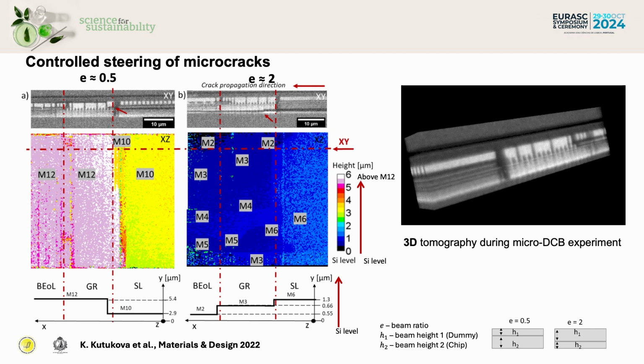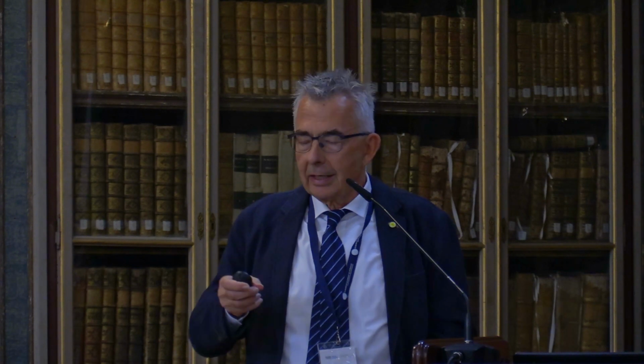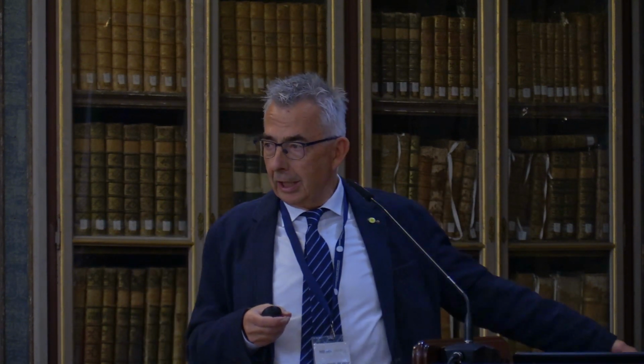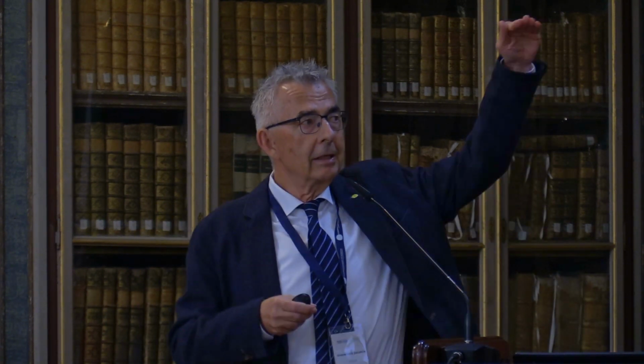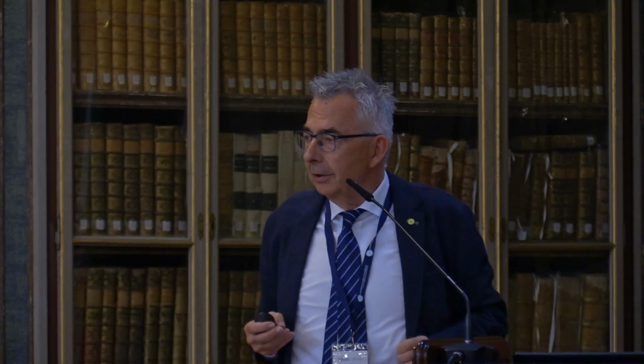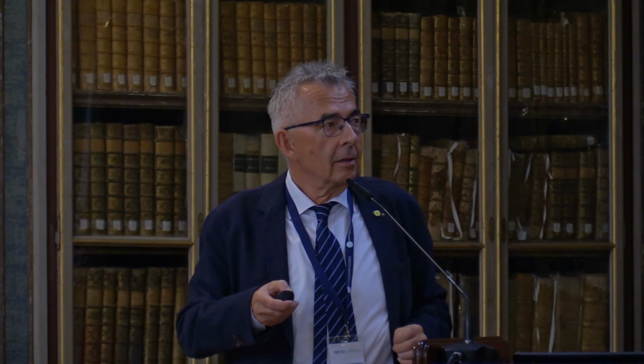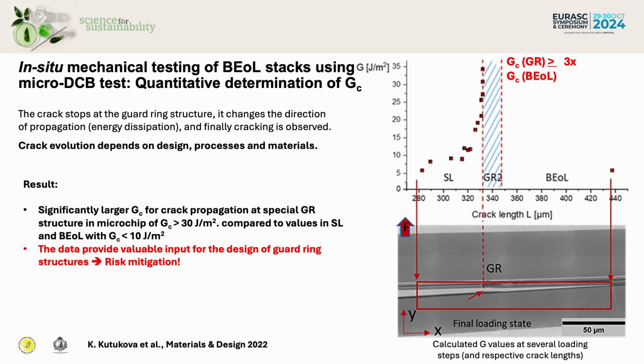And if you have a 3-dimensional set, you see on the left-hand side on which levels in the interconnect the crack is propagating. And you can steer the crack either to the bottom where the transistors are, that's terrible, or you can steer the crack to the top where the metal 12 is with 2 micron copper, or you can steer it into the guarding structure. This is what we are doing.